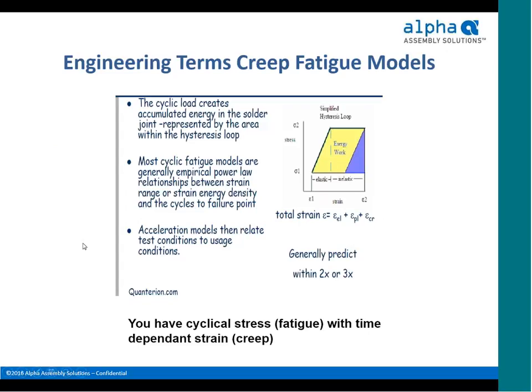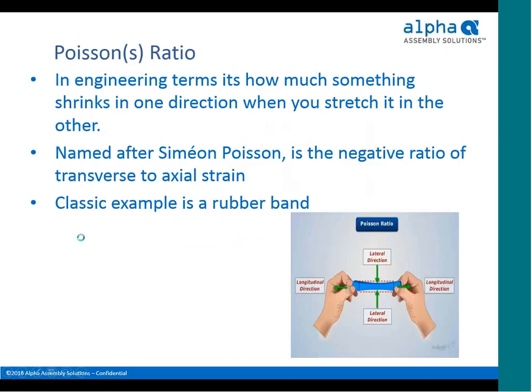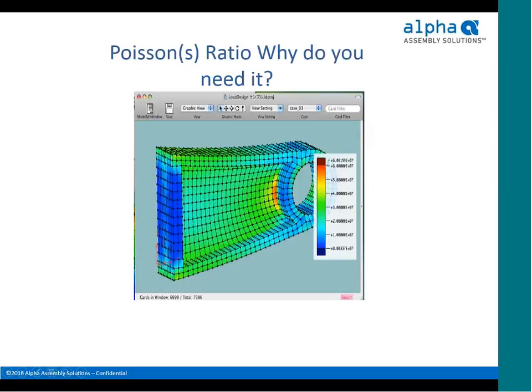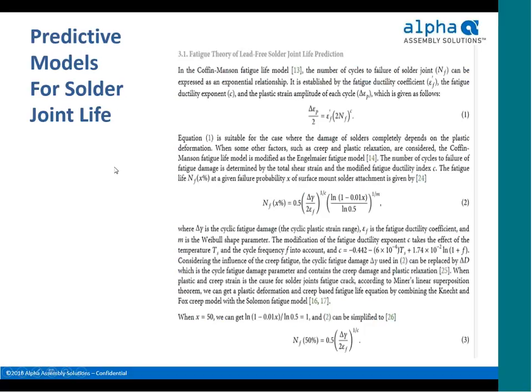So these cycles are time dependent. One of the things they use as well is the Poisson ratio, which is basically the ratio of elongation to narrowing. This can give you some quantification of the stress and strain applied at different thermal cycles, different temperatures. And why we care is what you see, say, in this connecting rod. There are different stresses at different areas depending on the kinds of stresses applied and how much elongation occurs at those locations. So all of this work eventually leads to predictive models for solder joint life.